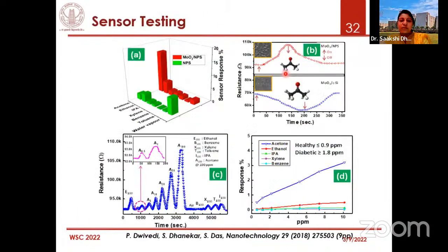What was observed was that molybdenum trioxide on porous silicon gave an extremely high response to acetone. But alcohol is generally always competing with acetone. Alcohol, methanol, acetone, they're always competing. So it's really hard to have acetone specifically detected if ethanol is present, unless its sensitivity is extremely high, which we could observe here. It went really high, around 18% sensitivity was achieved in comparison to alcohol being something like 3%.